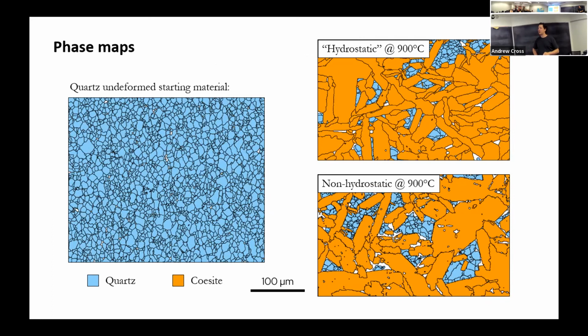Then we've got experiments where we quenched it halfway through the transition from quartz to coesite, under hydrostatic conditions and then under non-hydrostatic conditions. So we see we've still got our blue polycrystalline quartz aggregate here with about the same grain size as the starting material. And now we've got these big laths, these big tabular things, which are our coesite grains.